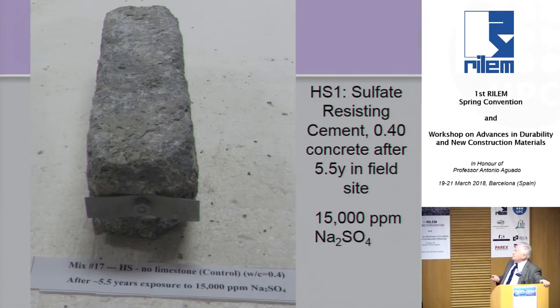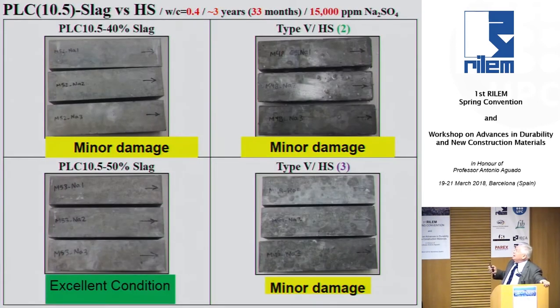That's a high sulfate-resistant Portland cement after 5.5 years to see just a more close-up of the damage that occurs. There's a different Portland limestone cement with about 10.5% limestone, again with 40% slag or 50% slag. Two different sulfate-resistant Portland cements.